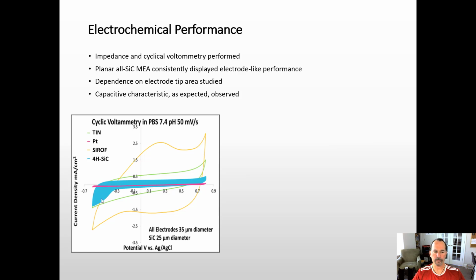here we see in this blue color the CV curve that we achieved. In magenta is platinum, so we're already exceeding platinum in terms of CV performance on our first demo device, and we're comparing it to Ti nitride and sputtered iridium oxide, which is shown here, which is quite a good material. And so we perform better than the platinum electrode for 4H.